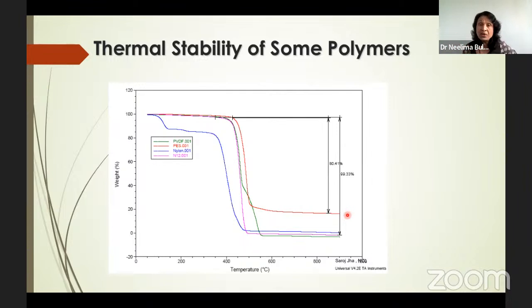But yes, it is important for a manufacturer, because the manufacturer will come to know that my material is stable up to 400. There is absolutely no weight loss in my material up to 400 degrees centigrade. But at 450 degrees centigrade, there is around 80% weight loss in my substance and some 20% residue remaining. See, such a simple experiment gave you such information for a manufacturer.